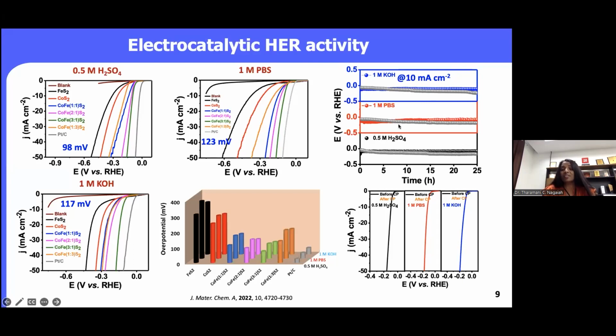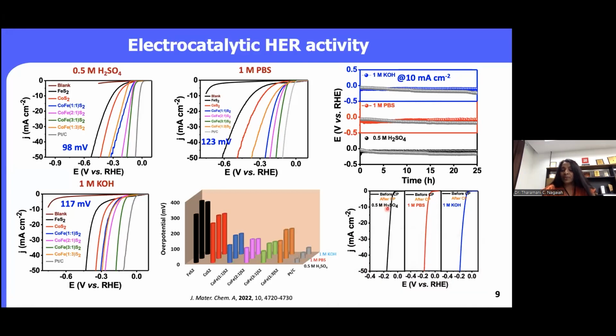However, you can see that there is a small decay with respect to the platinum carbon, both in the case of alkaline as well as in the case of PBS. After the long-term stability test, we again checked the hydrogen production, as you can see in the bottom graph here. As you can see, there is no shift either in the potential or decrease in the current, both in the case of the acidic media as well as in the buffer and the alkaline. That means the catalyst is quite stable even over the time scale of 25 to 30 hours.